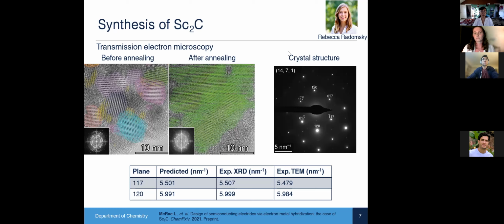My second question is corresponding to Wenshao's question. How do you improve the conductivity experimentally? Yes, so what we're trying to do now is increase the purity of the sample. And we think that the reason we still have some amount of the cubic phase is because we're getting oxygen into the sample, during transfer processes and even during annealing.